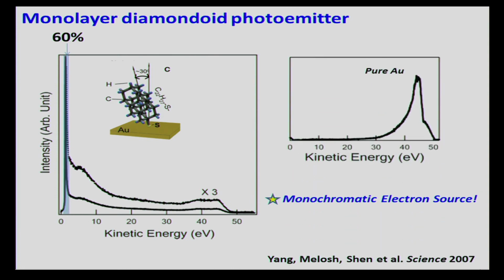And just to compare that with a bare gold surface where you don't have the diamondoid, again, you have this very broad peak spanning about 20 eV, whereas if you have the diamondoid on the surface, the peak width is only about 0.2 eV. So we're really creating sort of an energetic funnel where we take a very broad range of electron energies and just squeeze them into a really sharp peak. So instead of throwing away all these electrons that don't have the right energy, now we can concentrate them into the single peak and make them all useful.